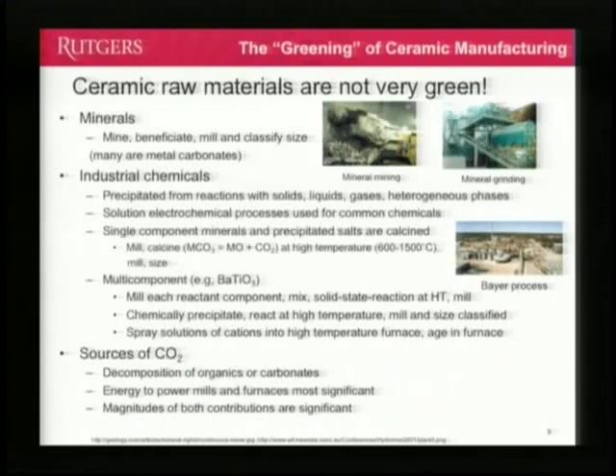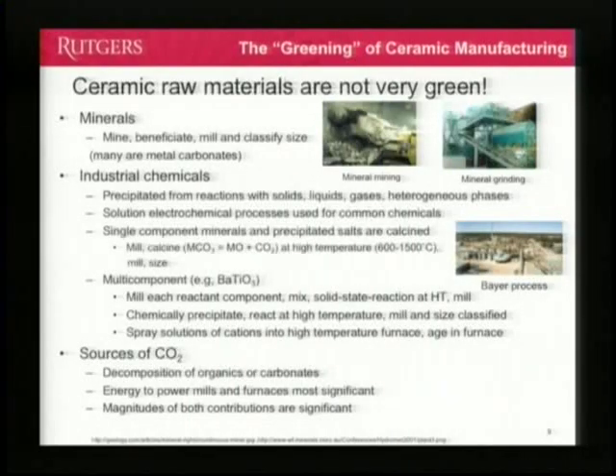Then we've got to grind this stuff just like we had with the original minerals. And then after we're done grinding it, we do a high temperature reaction, as I mentioned. In this case, you may actually go through, in many cases, two different high temperature reactions before you're done, which would actually add another 30% more CO2 to the air. So some people get around that by spraying things into high temperature furnaces, but then you're spending a lot of energy evaporating water in addition to all the other stuff I already told you about.